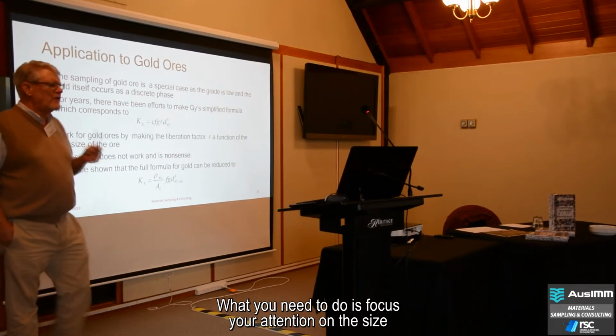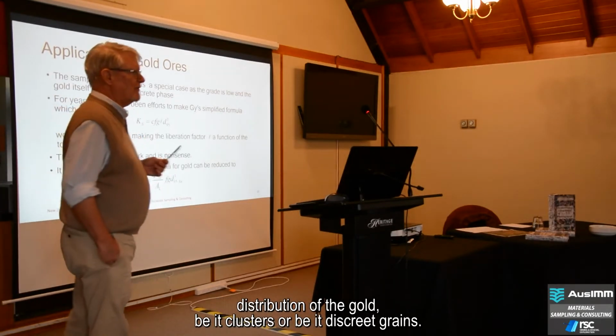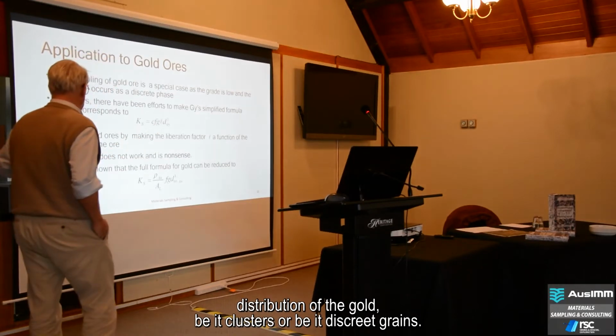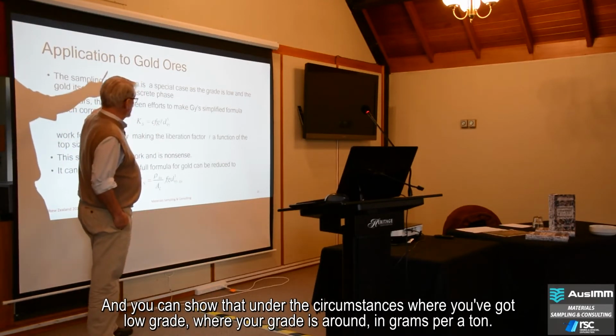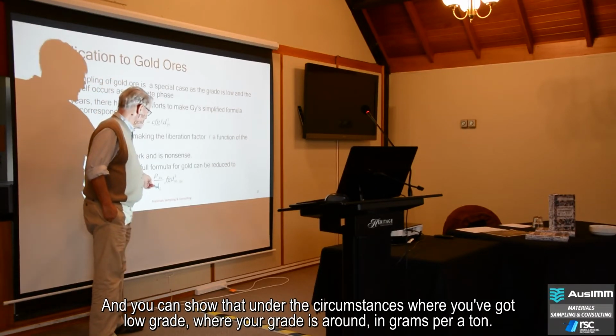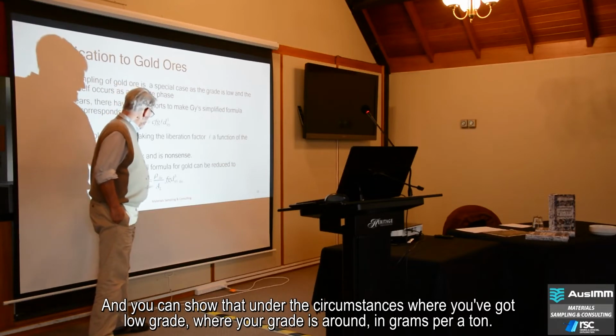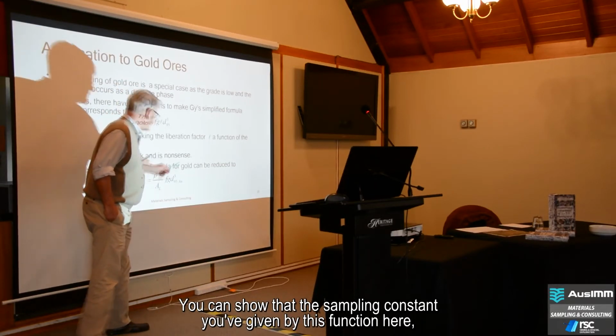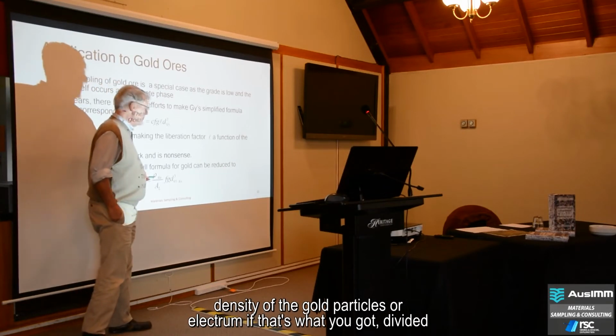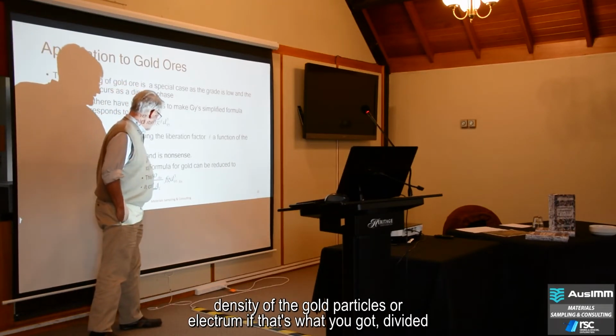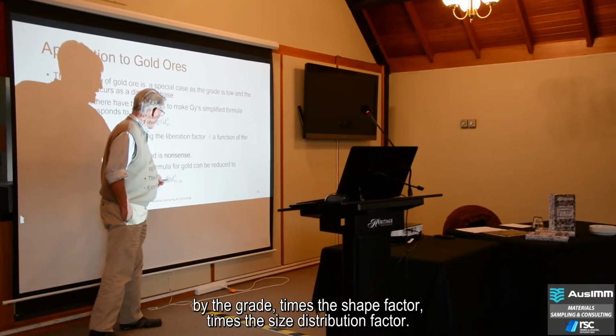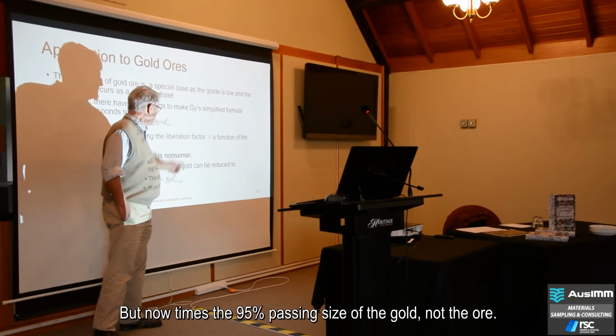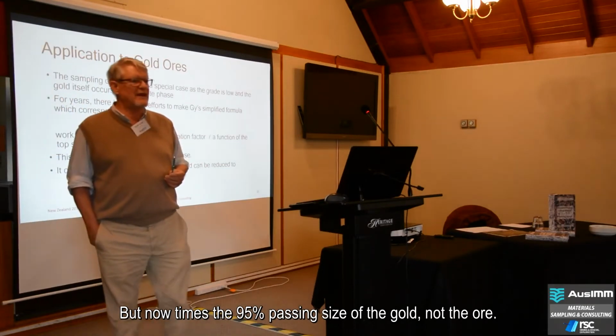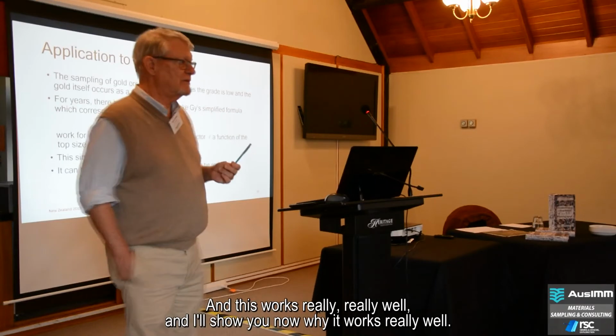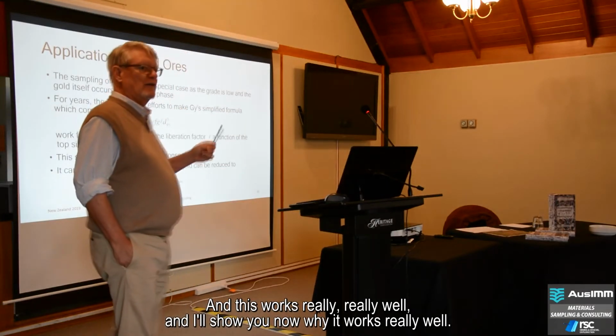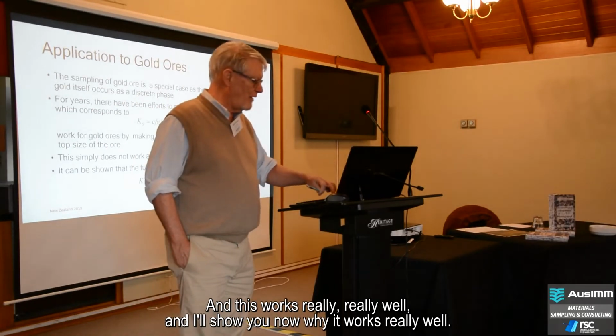What you need to do is focus your attention on the size distribution of the gold, be it clusters or be it discrete grains. And you can show that under the circumstances where you've got low grade, where your grade is around grams per ton, the sampling constant can be given by this function here: density of the gold particles, or electrum if that's what you've got, divided by the grade, times the shape factor, times the size distribution factor, but now times the 95% passing size of the gold, not the ore. And this works really, really well. And I'll show you now why it works really well.